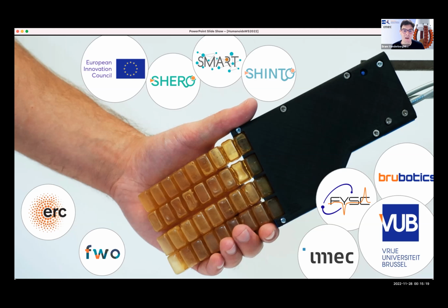Moreover, for thinner material, it's much stronger. We're still working on having multiple nozzles in order to mix different materials together, because imagine you can have different properties, stiff material, very soft material. You can add fillers. The idea is to create printers where we can print with a voxel-based concept, where at the moment we have made cubes. But the idea is to go to a smaller scale, so that you can have different materials printed together. And because the interface is so strong, we can completely mix all those different materials. That's the longer term vision of this additive manufacturing route, which has unique capabilities due to the self-healing property of the material, but also the multi-material bonding, which I think is also very important.